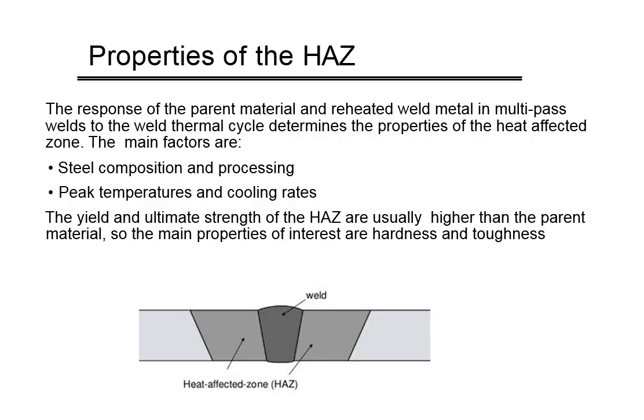Properties of the HAZ. The response of the parent metal and reheated weld metal in multi-pass welds to the weld thermal cycle determines the properties of the weld heat affected zone. The main factors are steel composition and processing, peak temperatures, and cooling rates. The yield and ultimate strength of the HAZ are usually higher than the parent metal, so the main properties of interest are hardness and toughness.